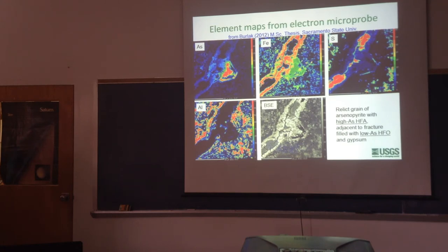So there's a vein here with iron that's low in arsenic. There's iron and arsenic together in the middle here, which is the old arsenopyrite. And we see that there's almost no sulfur left here in the original arsenopyrite grain. You can see that it's replaced largely by iron oxide, but some of that iron oxide is very high in arsenic. But you can tell from the shape of this that this was originally an arsenopyrite grain.